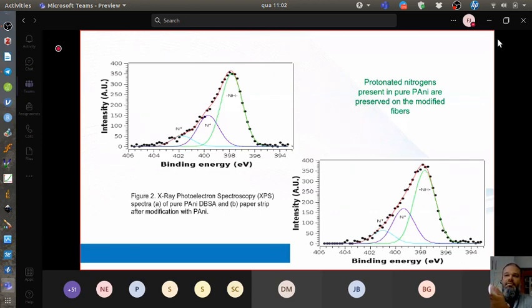In this slide, we have the X-ray photoelectron spectroscopy results of these materials. In the left corner, we have the PANI, and in the right corner, the cellulose modified with PANI. As we can see, there are 2 protonated nitrogens in both cases, and it is very nice to us because it is showing that before the modification, we have 2 kinds of protonated nitrogens, and after the modification of the cellulose, these 2 protonated nitrogens were preserved. So we can imagine that PANI on the surface will work as we are expecting.